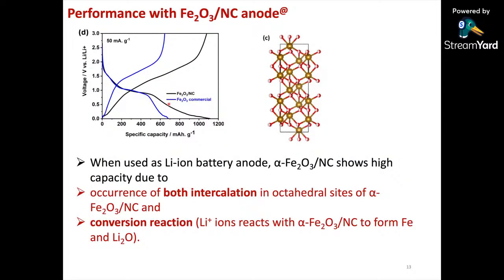Let us first compare the performance between Fe2O3 commercial and Fe2O3 NC, and you can see that from 700 milliampere hour per gram, the specific capacity has been enhanced to almost 1100 milliampere hour per gram with all identical parameters. This is mainly because lithium ions can get intercalated in the octahedral sites of this alpha Fe2O3 and C, as well as a conversion reaction occurs. Therefore, these Li+ will be interacting with Fe2O3 here to form Fe0 and Li2O.